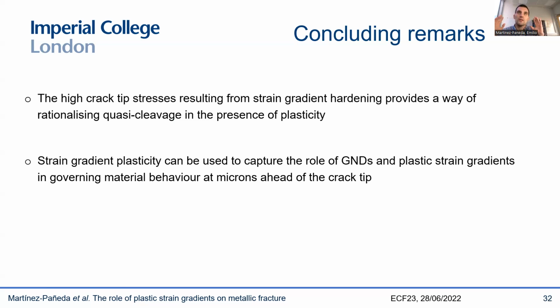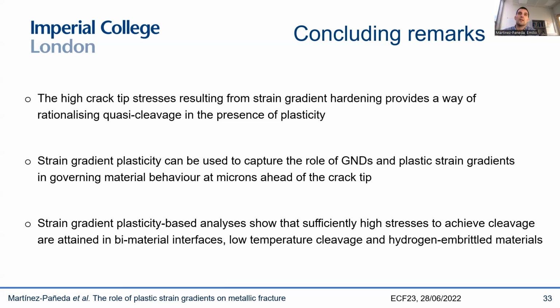So we can use this class of constitutive models, strain gradient plasticity models, to capture the role of GNDs in plastic strain gradients. We calibrate them with experiments, and then we use them to predict what's going to happen ahead of a crack. And we have shown that by taking this into consideration, we can explain experiments showing the brittle failure of hydrogen-embrittled materials. We can explain low temperature cleavage, and we can also explain the fracture of bimaterial interfaces, among other phenomena.